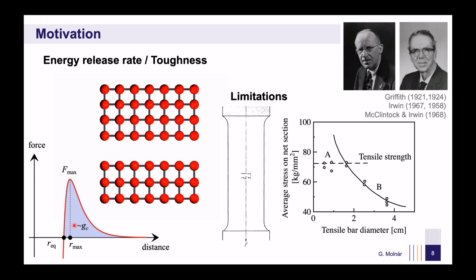Later, George Irwin provided experimental validation of Griffith's theory. He demonstrated that when a specimen is sufficiently large, it behaves as predicted by Griffith's energy-based criterion. However, when the sample is small, its resistance is better described by a stress-based failure criterion. Irwin was also the first to introduce an approximation for the transition length scale.